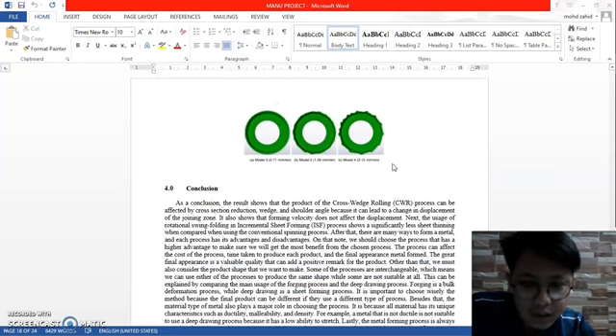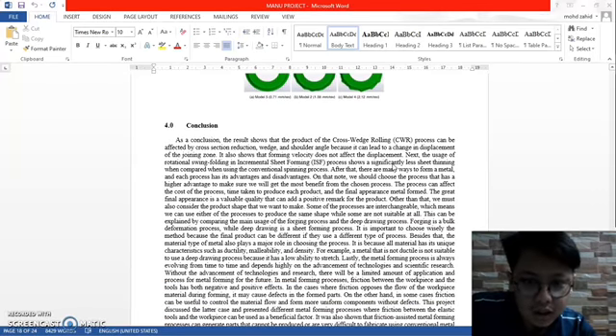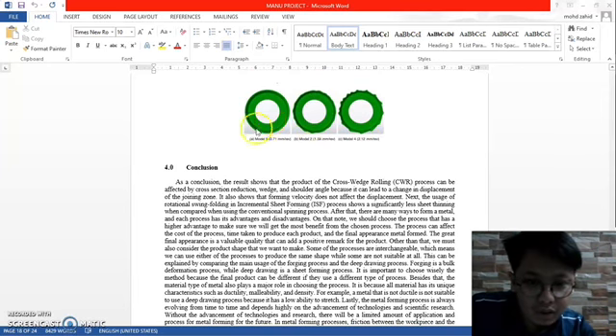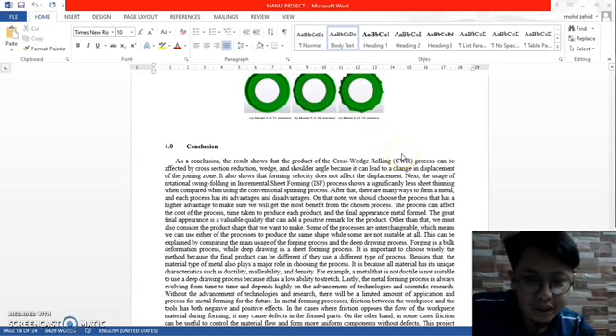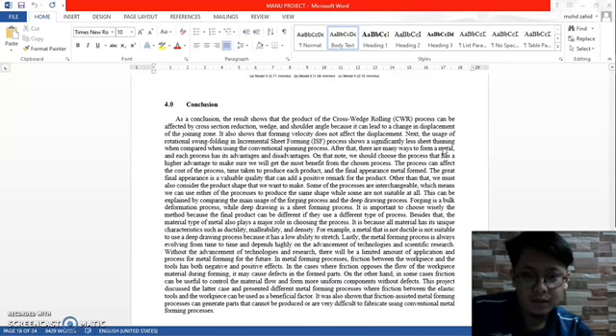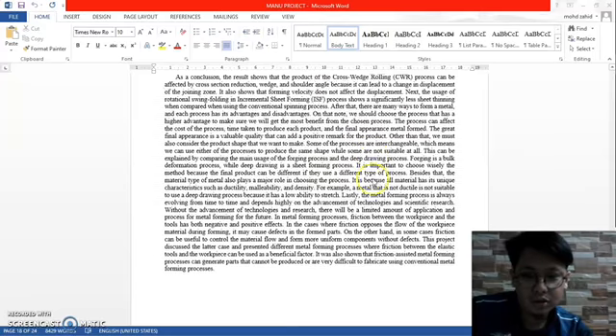As the conclusion, the results show that the product of the cross wedge rolling process can be affected by the cross-section reduction, wedge and shoulder angle because they can lead to a change in displacement of the joining zone. It also shows that forming velocity does not affect the displacement. So yeah, that's our conclusion.